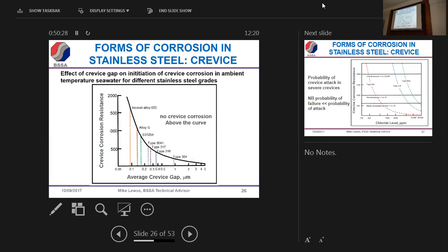316, it's smaller. You can go right up to a nickel-based superalloy and you're at a very small gap size. Now, the reality is that most fittings, you'd be hard pushed. Usually the gap sizes range between 0.2 and 0.5, just because of the tolerance on the fittings. It would be virtually impossible to get a gap size like this.